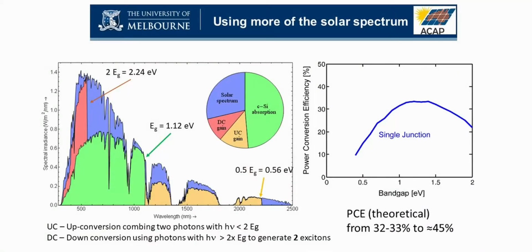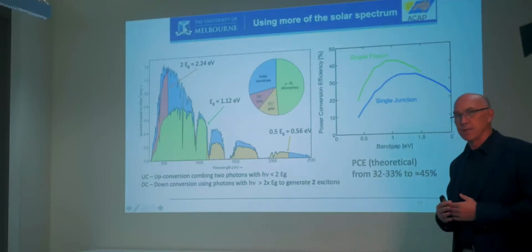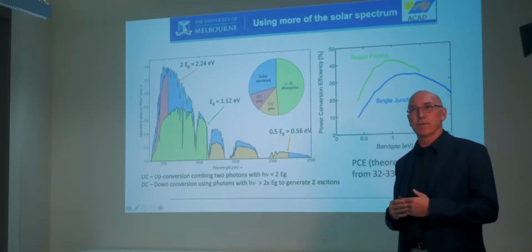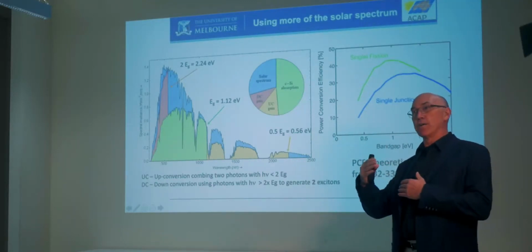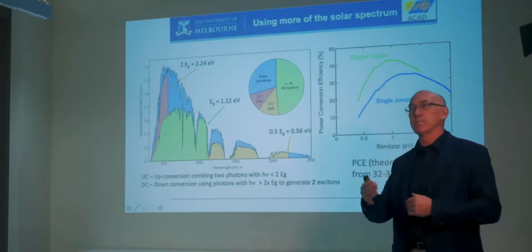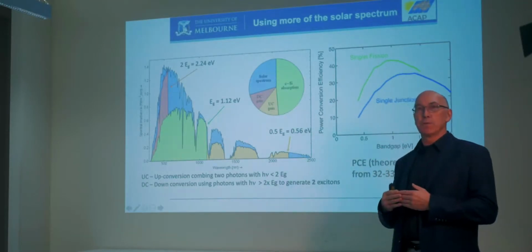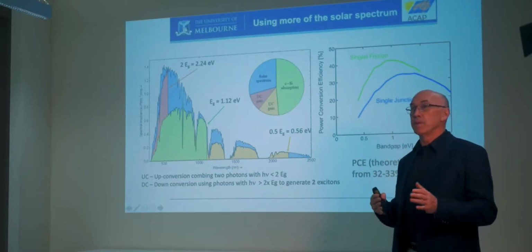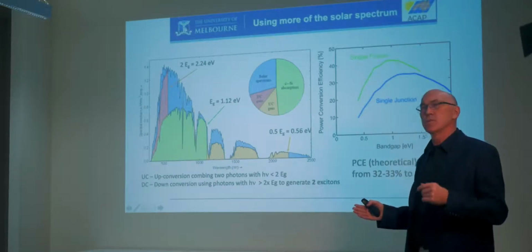Depending on your calculations, there'll be a little bit less on both ones. So in theory, if we can do this down conversion, we may be able to get up to 12% efficiency increase. If we think back to those commercial solar cells, we're not looking at getting a 12% increase. We would like to target a 5% increase. But that's an absolute 5% increase, and therefore that's a 25% increase in power per solar cell for the same cost effectively, if we can do it. So that's the driving force of why we want to do this.